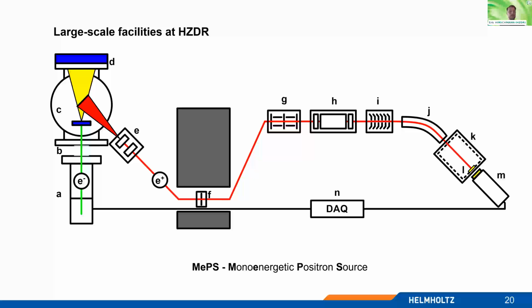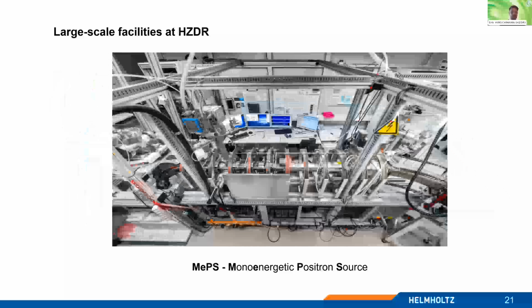This is the first of our beam-based positron facilities, which is called MePS, the mono-energetic positron source, which enables us to measure thin films in the range of 10 to 1,000 or 2,000 nanometers approximately, depending a little bit on the density and on the atomic number of your sample. But in principle, this is the range we can investigate. And this is the setup in real.